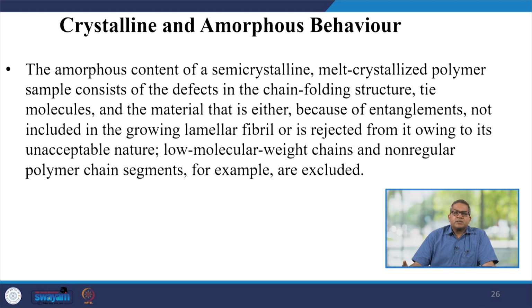The amorphous content of a semicrystalline or melt-crystallized polymer consists of the defects in the chain folding structure, the tie molecules, and the material that, because of entanglement, is either not included in the growing lamellar fibrils or is rejected from it owing to its unacceptable nature.